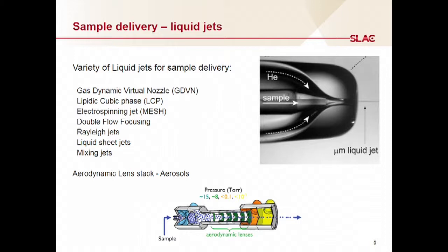And because of that, you can have very low sample consumption, because you don't need to have huge amounts of sample in order for it to flow focus using this helium. You have an additional outside jet that helps with the focusing. There's Rayleigh jets, which are very big jets. There are liquid sheet jets, which can be very broad, which is what it sounds like, a liquid sheet, about 10 microns in thickness if you wanted to do liquid scattering experiments.